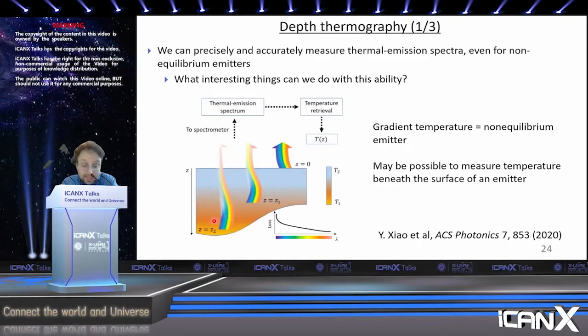than the thermal radiation from beneath the surface, not only because the temperatures are different, but because the sample is necessarily going to have some optical losses that are wavelength dependent. Therefore, the spectrum of light that comes out is going to have different spectral content if it comes from the depth of the object than from the surface of the object. And so this is potentially an exciting opportunity to do some computational work and to retrieve the underlying temperatures. This is from a publication from last year.